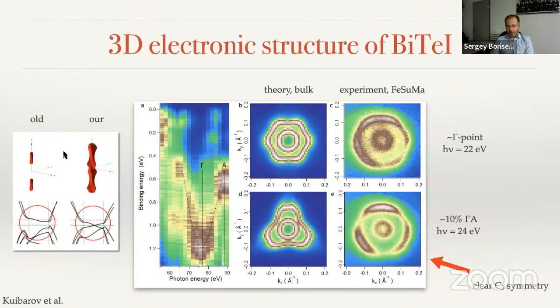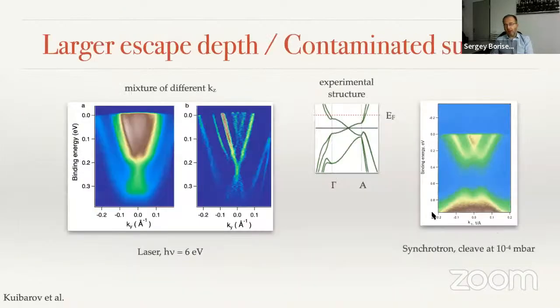So that's, again, this kind of scenario certainly fits our picture rather than the old picture. Another thing is that we measured the spectra also using the 5.9 eV laser, meaning that this is the most bulk sensitive spectra of bismuth tellurium iodine ever measured, because the previous data included the laser data with the 7.7 eV. So this is the lowest energy data, usually considered as the most bulk sensitive.